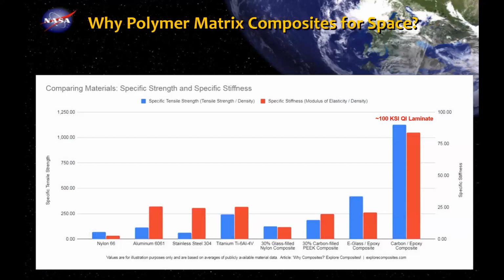And so this is, everybody sort of knows why, but I just want to highlight composite materials. People think of strength, but if you look on the right, this is the specific tensile strength on the vertical axis, and it's got both that and the specific stiffness. Strength is in red, and I'm sorry, strength is in blue and stiffness is in red. And for a 100 KSI common quasi-isotropic polymer matrix composite laminate, we're basically out of the water when it comes to strength and stiffness.